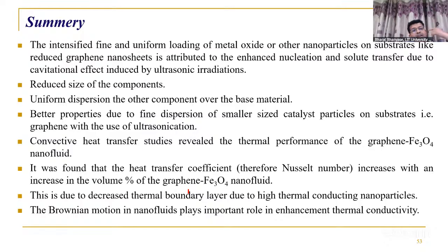So in summary, you can say fine or uniform deposition of metal oxide, that is Fe3O4, on graphene sheet is observed, because of enhanced nucleation and solute transfer due to cavitation induced by ultrasound. Then reduced particle size, uniform dispersion of Fe3O4 nanoparticle on RGO, and better properties due to fine dispersion.